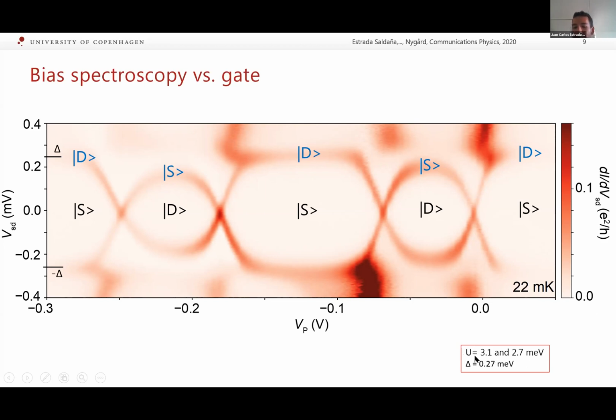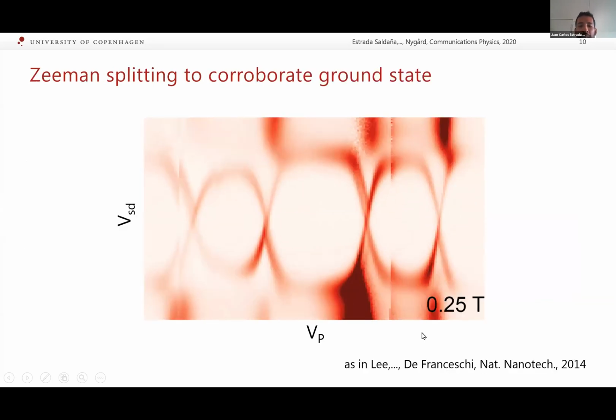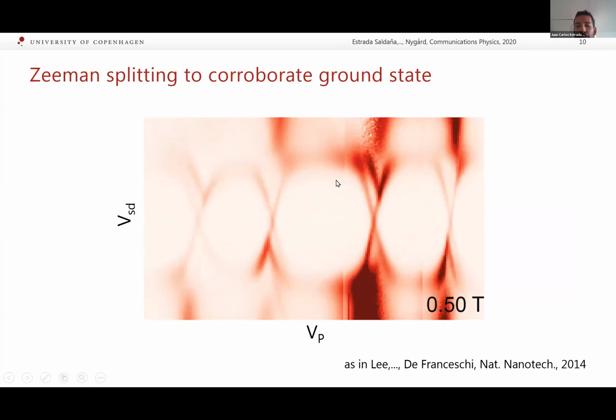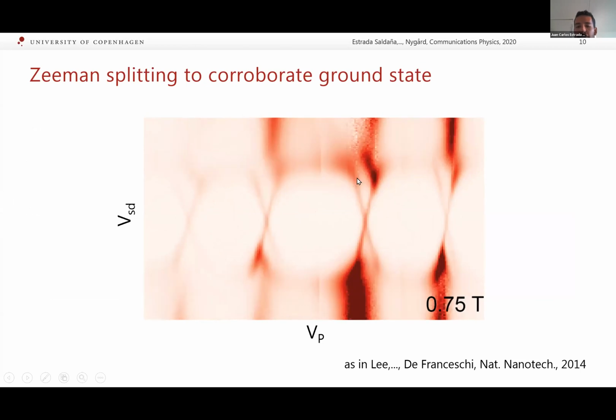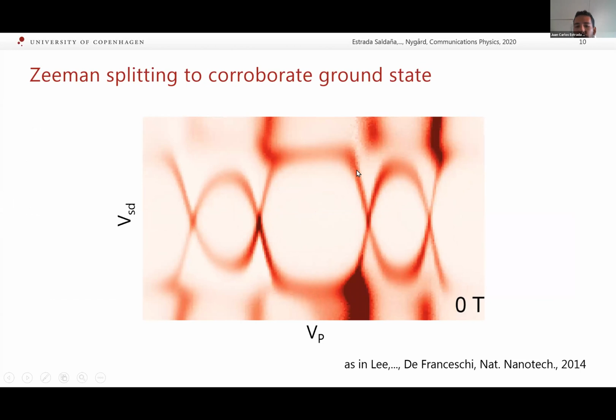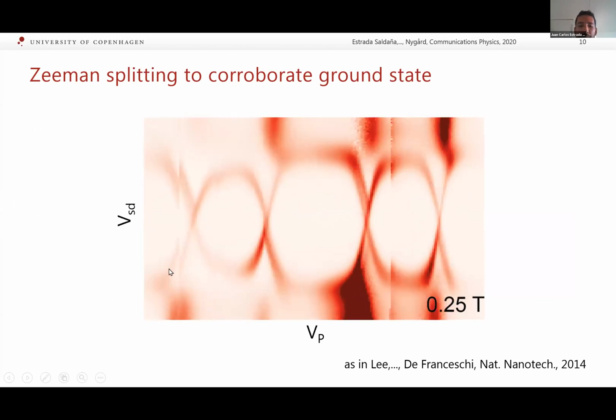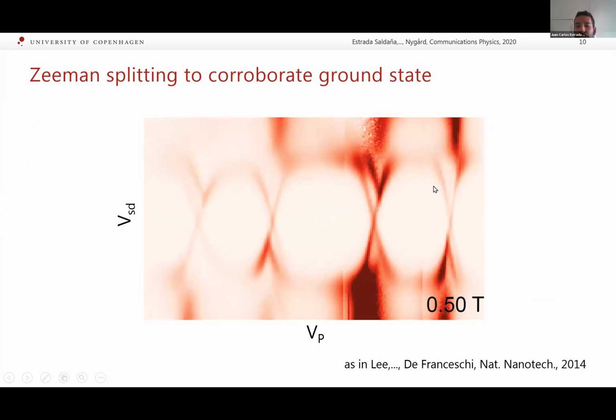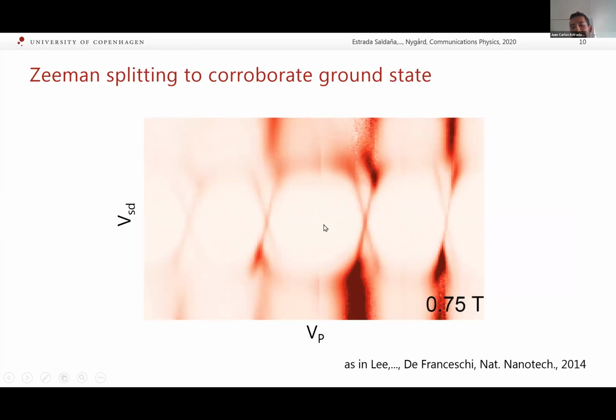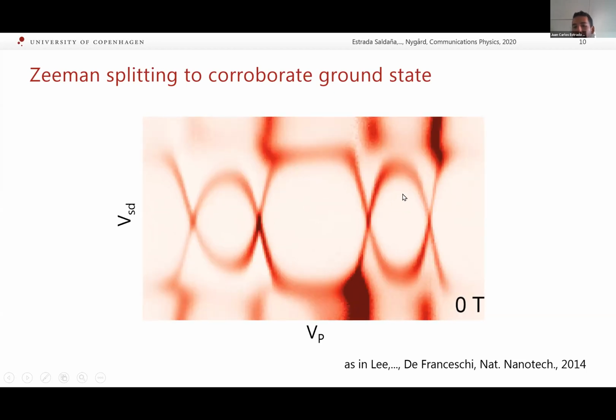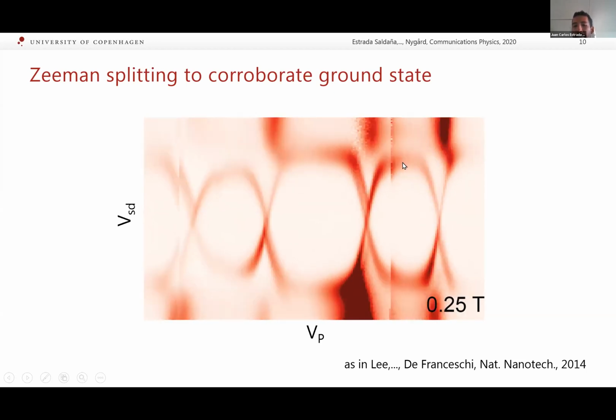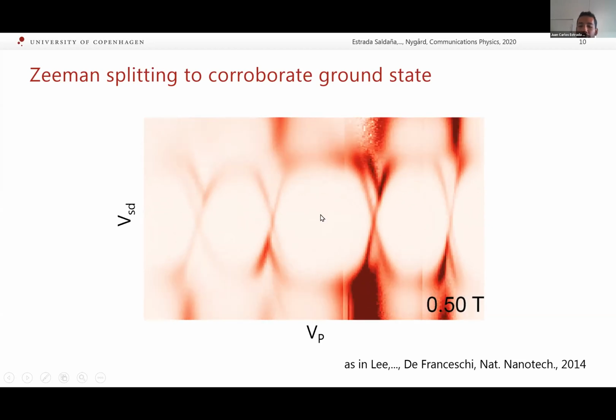We're well inside of the YSR regime, where the charging energy is bigger than the gap. So next we corroborate what the ground state is, and we do this by applying a magnetic field, and we split the YSR states. So in the singlet ground state, we have two doublet spin-resolved excitations, and we see a splitting here. We see a splitting here as well, and here, and there, and there. On the contrary, loops which have a doublet ground state don't split in magnetic field, and that's how we recognize which ones are doublets and which ones are singlets.